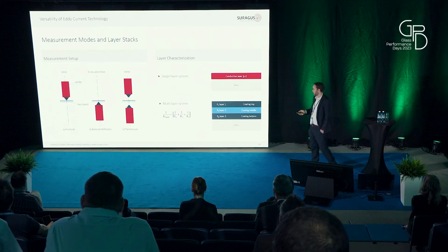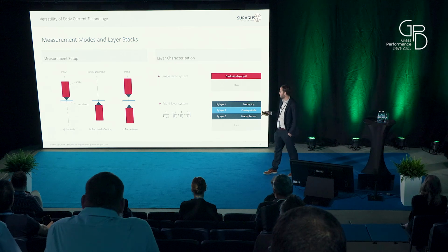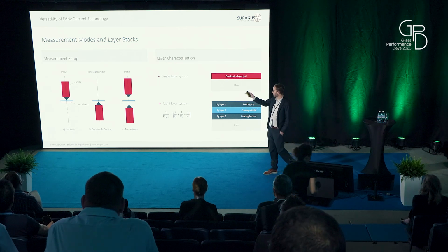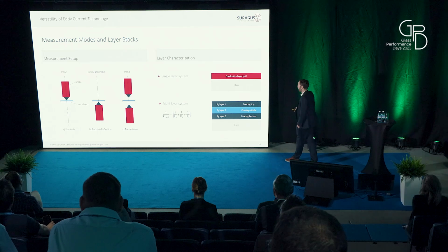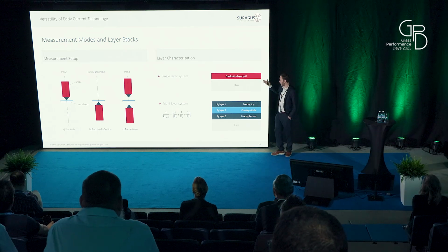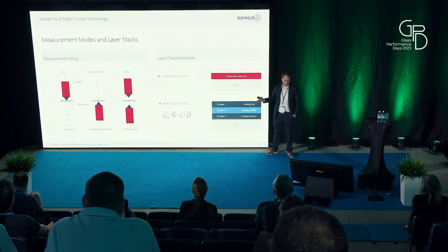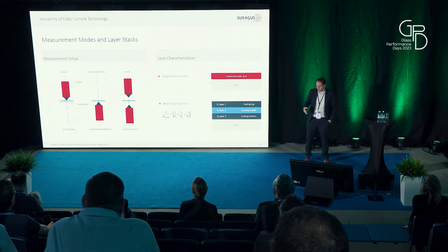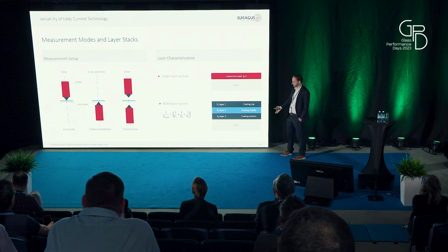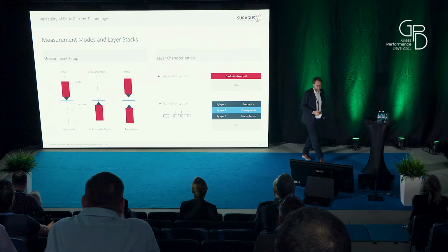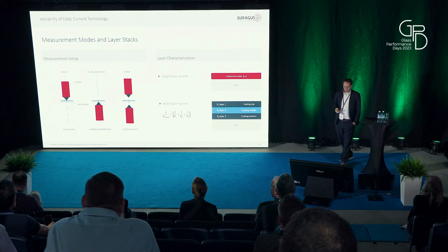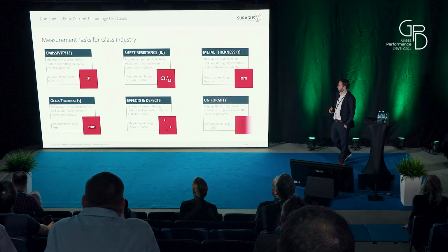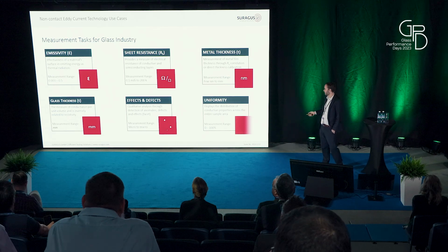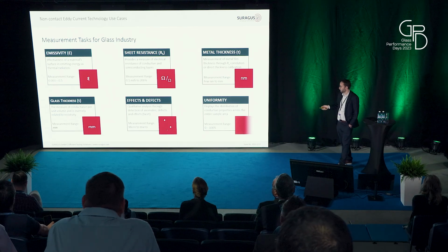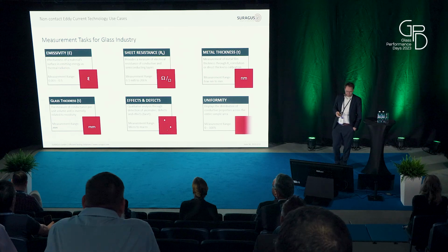There are different setups. It can be measured only from the top, like in the portable, but it can also be measured from the bottom or also in transmission mode. And it can be applied for single-layer systems, and it can also be applied for multi-layer systems, like in the LowE stack. There are different silver layers, and basically the tool picks up all the silver layers which are there and calculates the result. It's not only applied for emissivity measurements, but also sheet resistance, metal layer thickness, defects, uniformity. We also characterize laser scribing, and an indirect effect is also glass thickness measurement.